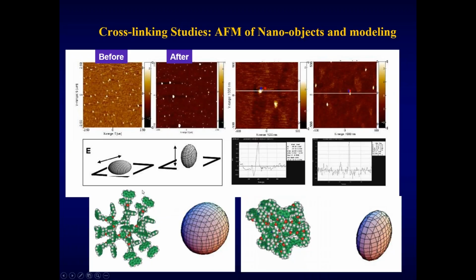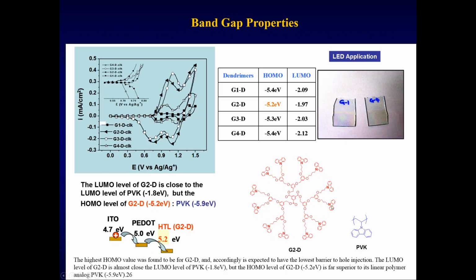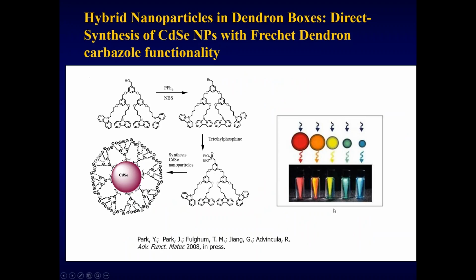Now what's interesting here is that when we hybridize the cadmium selenide and the carbazole, we observe a decrease in fluorescence of the carbazole group, but an increase in the fluorescence of the cadmium selenide unit. So this is an indication of a charge transfer mechanism instead of an energy transfer that was observed, let's say, earlier with the gold nanoparticle. That means that this species here can have charge generation perhaps through irradiation with light, or photovoltaic effect, which we did not have an opportunity to demonstrate as a device.